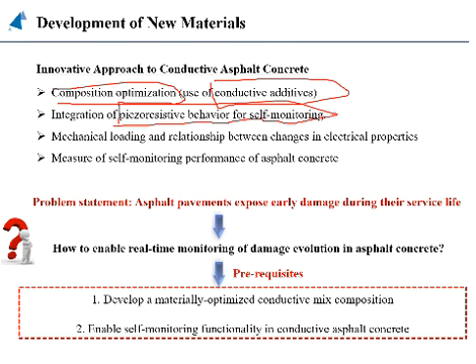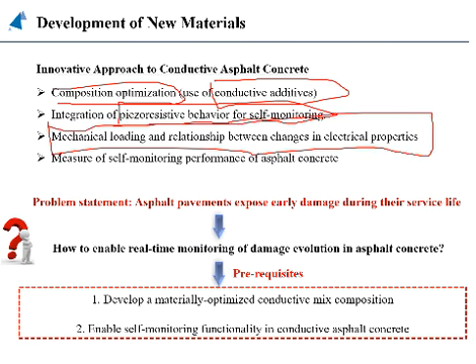This type of mixer was different from the conventional mixer because the conventional mixer just gave me the mechanical performance. But when I added some fibers and conductive additives to the conventional mixer, I modified its internal composition. So what did this type of mixer perform for me? In addition to the mechanical performance, it also gives me information about its internal condition through changes in electrical resistance, which is basically called the term FCR.